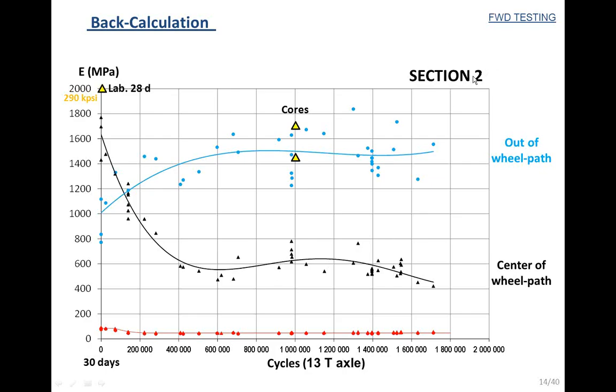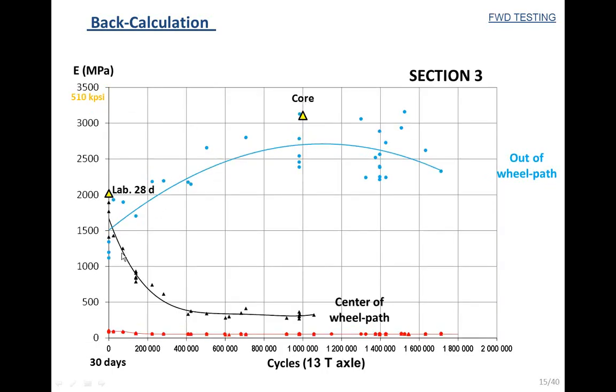So this is for section 2. Section 2 is stiffer than section 3. And here we have the result for section 3. For section 3, you can see that the modulus at the beginning of the test is also around 1500 megapascal. These black points correspond to the loaded line of section 3. Again, you can see a clear decrease of the modulus during the first half of the test. In this case, the modulus got stable around 400 megapascal, which was also surprising for us because this is a relatively high value.